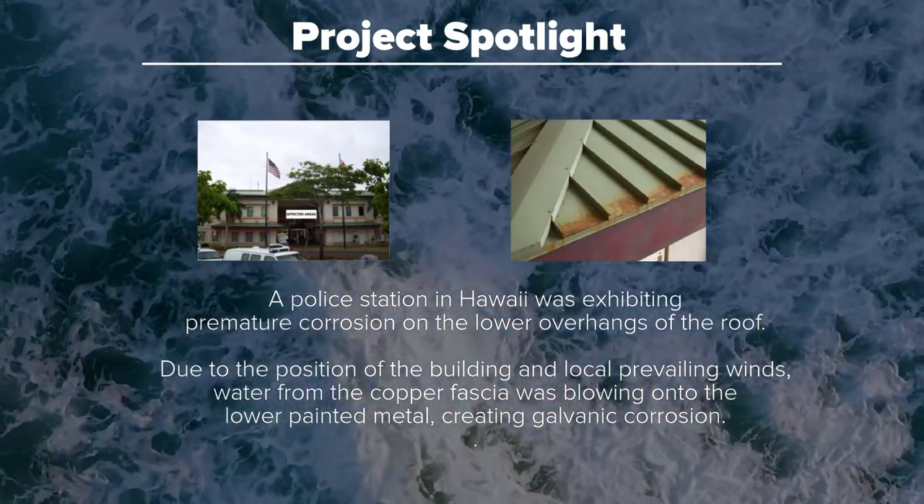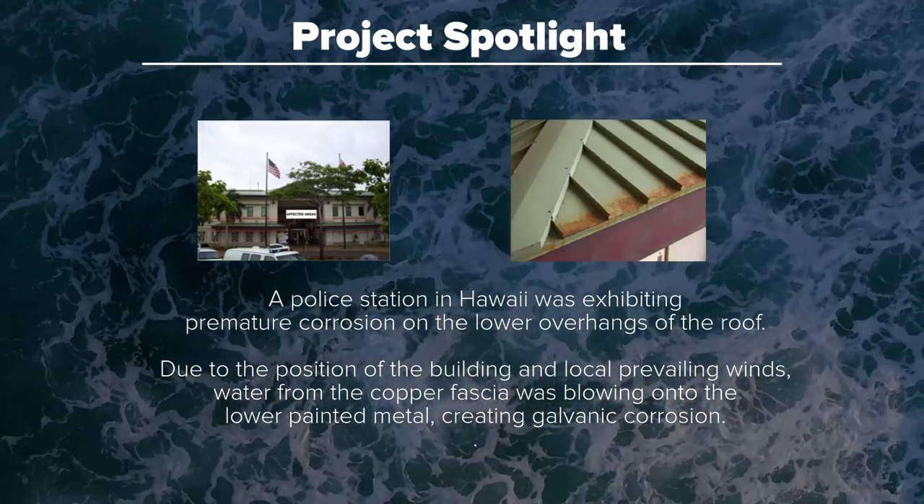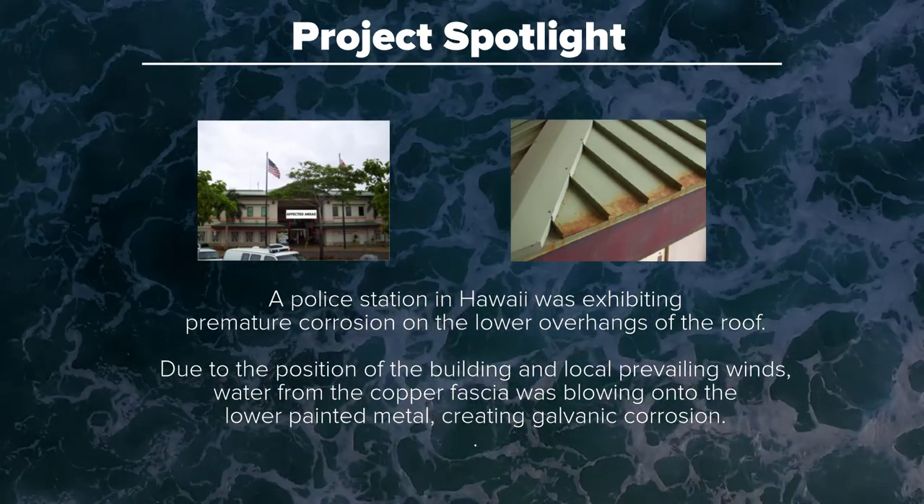Were there also examples with copper or treated wood? Those are problematic regardless of environment. Copper is very corrosive to coated steel — there should not be any kind of runoff or contact between them regardless of environment. Most wood that's been fire-retardant treated uses a copper solution, and that copper can leach out. If it's allowed to drip from, say, a wood deck down onto metal panels, you will get accelerated corrosion. But that could occur anywhere, not just in a marine environment.